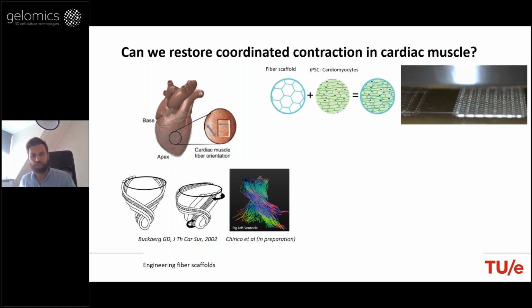So what we tried to do was basically to explore the use of another nozzle-based printing technique, in this case, what we call melt electrowriting. So basically a widely known technique probably for some of you, that merges the principles of extrusion-based printing with electrospinning, but in this case, we are not dissolving any polymer. So we are basically just melting a polymer. So combining the forces of pneumatic extrusion with an electrical field, we can achieve very thin polymer filaments that have diameters that span from submicron scale to a few microns, like 10, 20 microns. So in this case, we look at hexagonal shaped scaffolds that we combined with iPS-derived cardiomyocytes, and then we investigated the mechanical function of these constructs and the effect of geometry on restoring seeded cardiomyocytes maturation and organization.